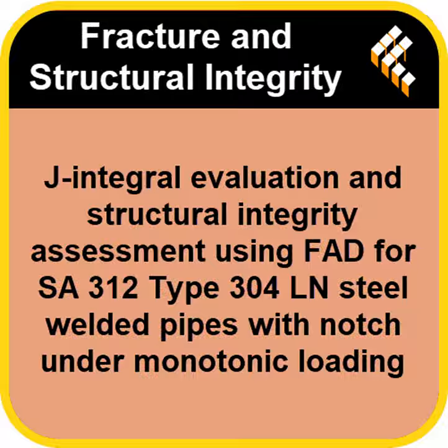What did they vary? Okay, so they tested varying several key factors. They looked at crack lengths, varying them up or down by 0.5 millimeters. Tiny change. Yeah. Pipe thickness up or down by 0.25 millimeters. Again, small variations. Then they looked at the material properties: flow stress, varying it by plus or minus 25 megapascals, and the initiation fracture toughness, JIC, varying that by plus or minus 25 units. Okay, so varying both geometry and material strength and toughness slightly.